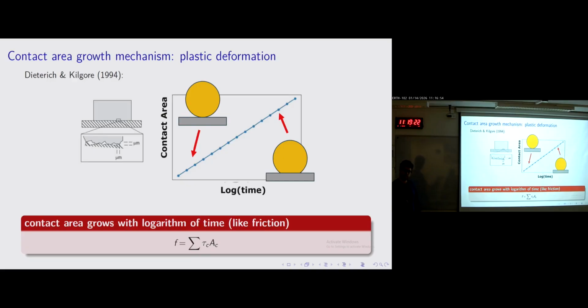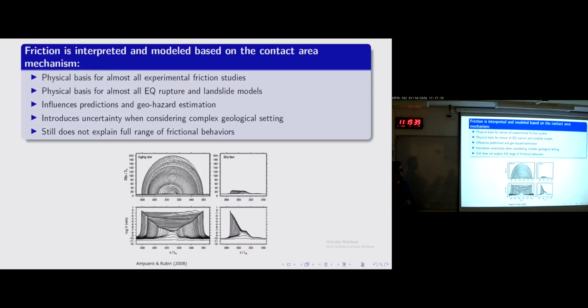Contact area grows linearly with the logarithm of time. This comes from the seminal work by Dieterich and Kilgore. It's a fantastic work, and that seems like the plausible explanation for why friction increases with the logarithm of time, right? And so that's a really nice physical framework. It works well with different materials, and so it's widely used and accepted in the friction community and in the earthquake modeling community. The idea is that the hypothesis, the contact area growth mechanism, controls the frictional aging, and goes into and explains almost all the experimental frictional studies today or in the past 20 or 30 years.